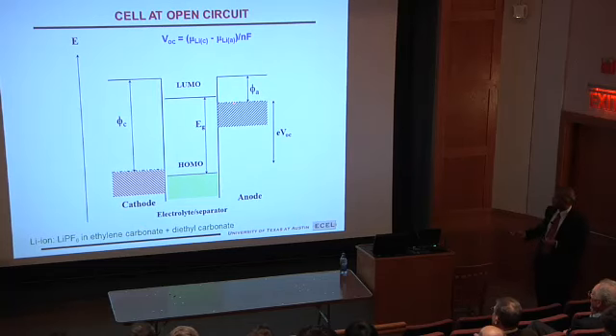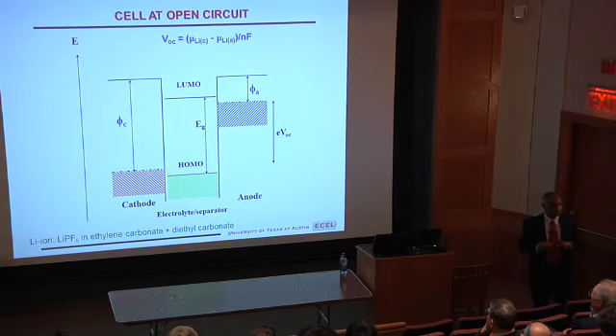So you can keep this as high as possible, keep this as low as possible. So you increase the separation, so you get higher voltage, that's 4 volt. We do have materials up to 5 volt, but these electrolytes are not good right now with that kind of 5 volt materials. So one of the challenges in the field is to come up with a new electrolyte that will have the window even larger than what we have now. Then you can increase the energy density more than what we have right now.